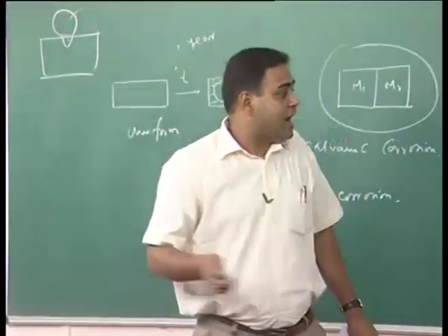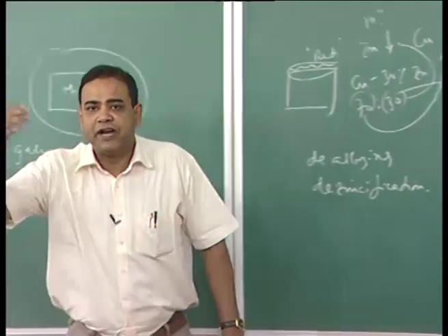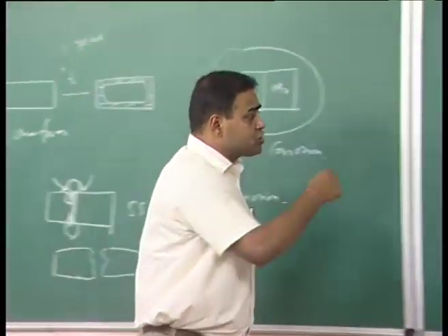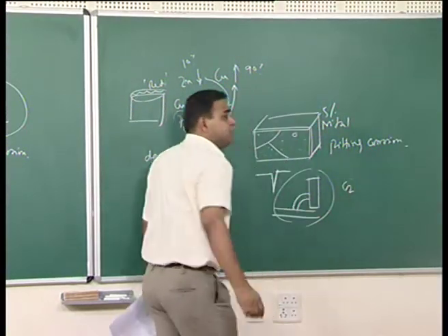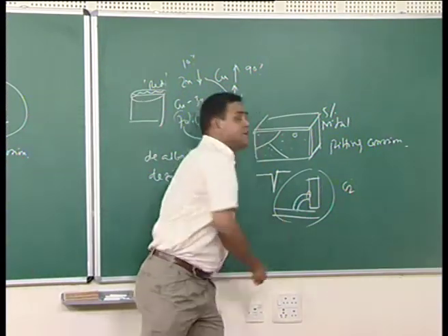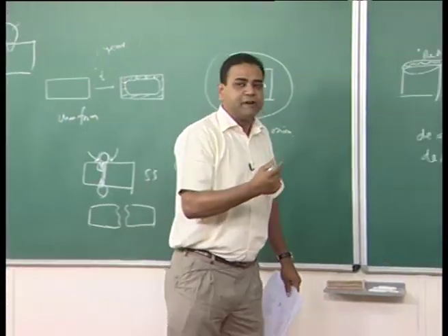When this friction is happening, it leads to high temperature, and locally the heat is increasing, and in the environment you have oxygen. So if the local temperature increases, the material in this region can get oxidized, and this oxide is very brittle in nature.